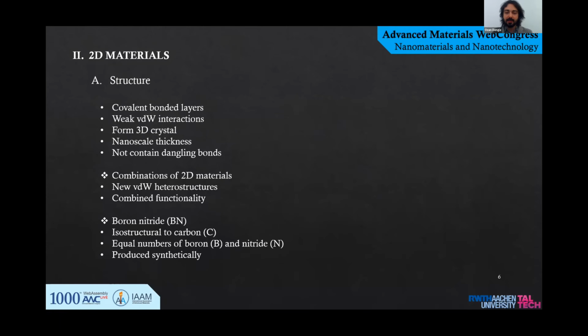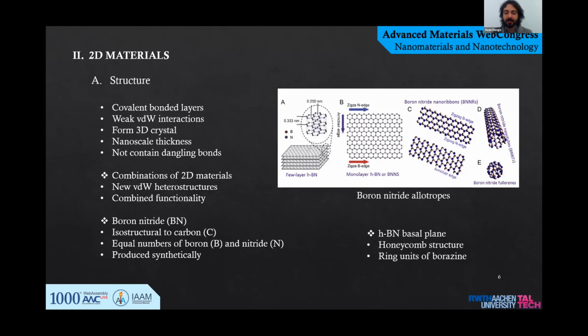My focus, BN, is isostructural to carbon and made of chemical compounds consisting of equal numbers of boron and nitrogen, which are produced synthetically since it's not found in nature. BN allotropes are shown here in the figure. To understand the concepts better, single-layer HBN is usually referred to as BN nanosheets, since its aspect ratio is small, and if it's higher, then they call it BN nanoribbons. And as you can see, the individual HBN basal plane is a honeycomb structure made up of ring units of borazine.